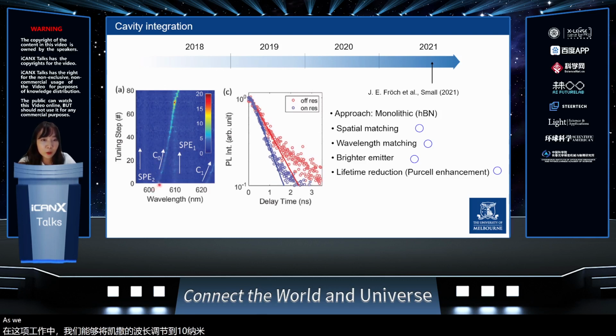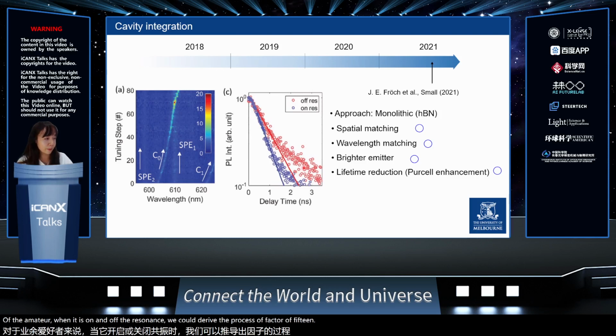As we gradually tune the resonant wavelength, indicated as C0 in this figure, the cavity mode eventually crosses the wavelength of the single photon emitter. When they finally couple, the enhanced PL intensity is observed. And finally, by comparing the lifetime of the emitter when it is on and off resonance, we could derive a Purcell factor of 15.